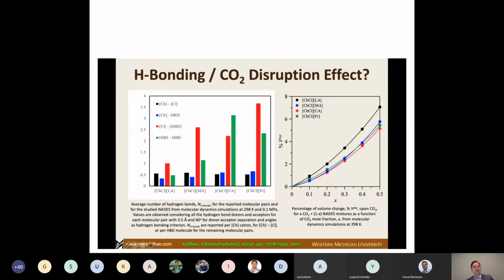We were able to see that in the case of the ionic liquid as a hydrogen bond acceptor, cation and anion, and the hydrogen bond donor, are still very much interacting with each other, even when CO2 is introduced to the system. So this was quite nice to observe, and it was kind of a relieving point, a proving point for us that we are really working with DES here when high pressure CO2 is introduced to the system.